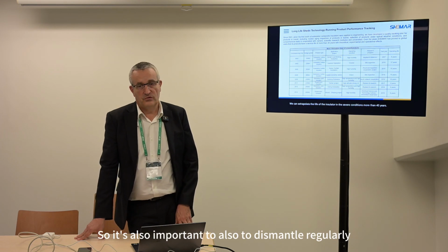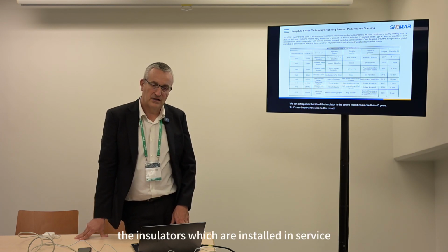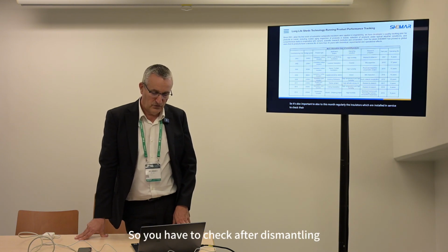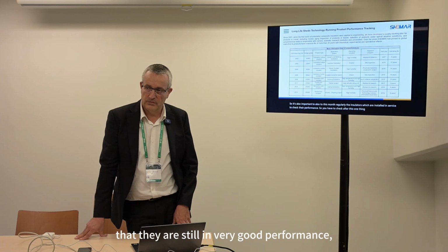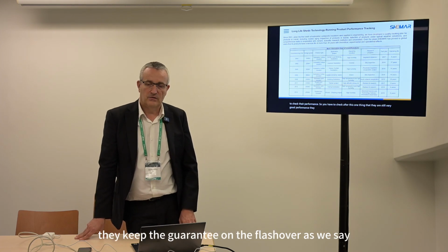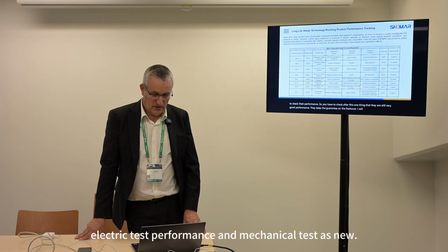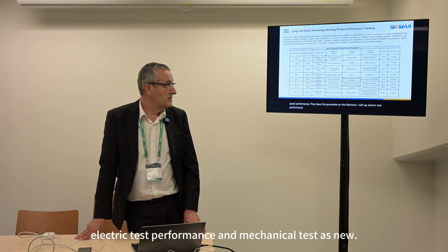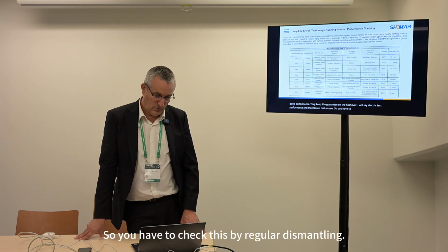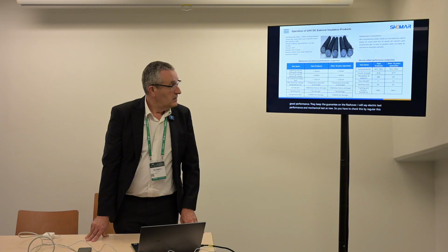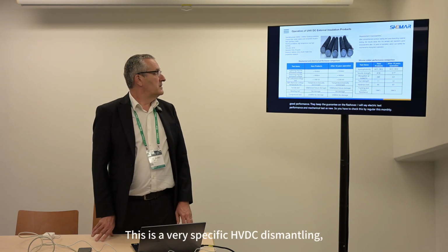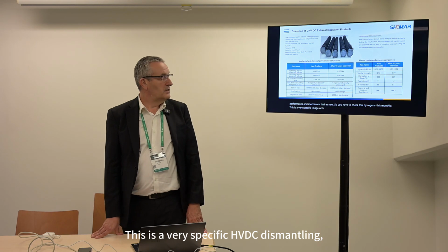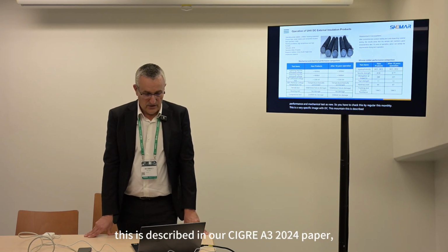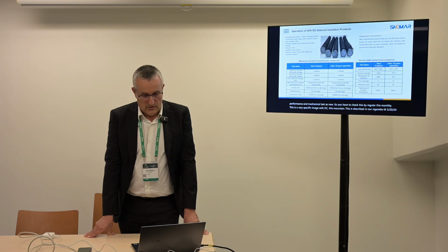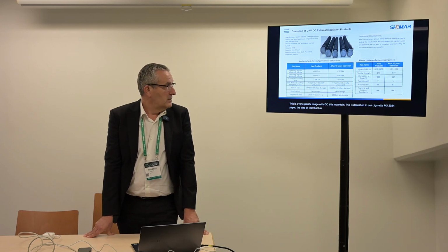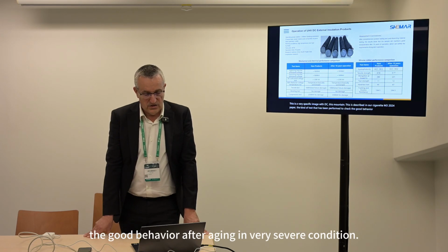It's also important to dismount regularly the insulators which are installed in service to check their performance. You have to check after dismounting that they still have very good performance. They keep the guarantee on flashover, electric test performance and mechanical test as new. So you have to check this by regular dismounting. This is a very specific UHVDC dismounting. This is described in our CIGRE A3 2024 paper, the kind of test that has been performed to check the good behavior after aging in very severe conditions.